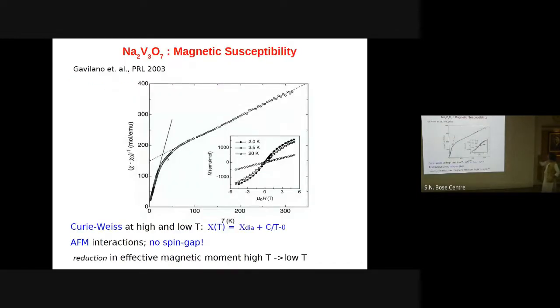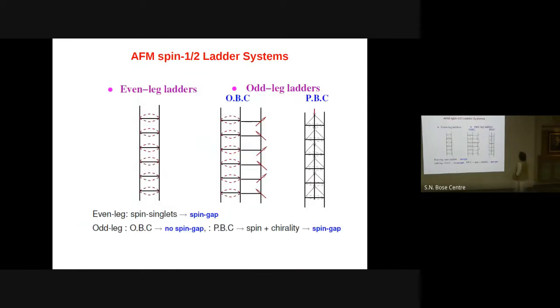So this is the magnetic susceptibility, and what it showed is that you can fit it with a Curie-Weiss law, but there are 2 different kinds of slope. There is a change of slope at a particular temperature, as you can see. And interactions are antiferromagnetic, as inferred from the theta. Most importantly, down to the very low temperatures they measured, there is no spin gap. So that was a bit surprising. Why is that? It is the following.